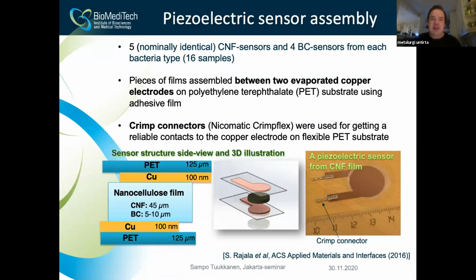What we did was make this kind of sensor elements where we sandwiched the nanocellulose films between two electrodes. On the bottom left you can see this structure. In the middle you have the nanocellulose film, either wood-based nanocellulose or bacterial nanocellulose, and we have evaporated copper electrodes on a PET plastic substrate, and used those as electrodes on both sides of the nanocellulose film. And here you can see the actual sensor on the right side.